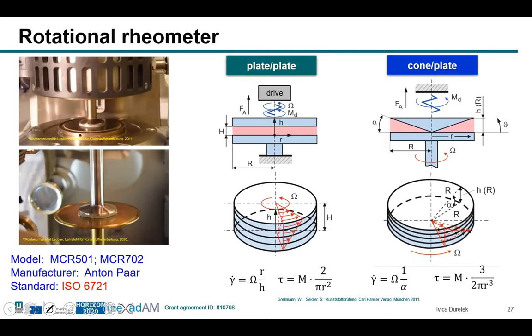This means we have the same shear rate at every section of the plate. In the plate-plate system, the shear rate is dependent on the diameter. The highest shear rate is at the outside of the plate. An advantage of the plate-plate system is that you can set the measurement gap between 0.5 and 2 millimeters, and you can measure highly filled or fiber-filled materials.